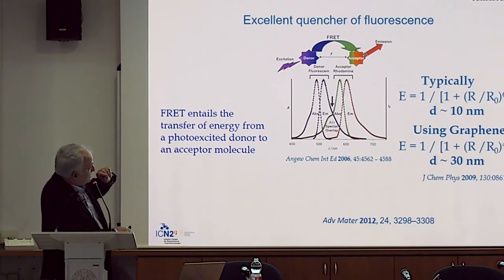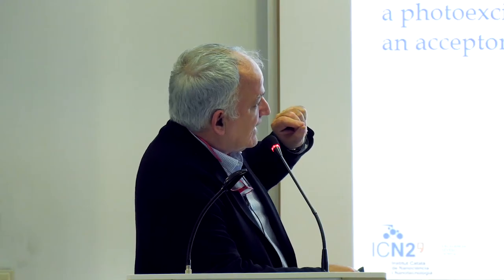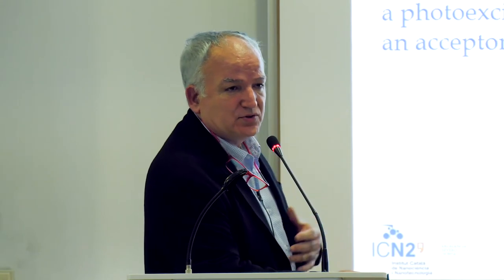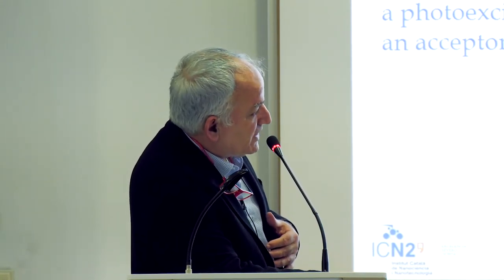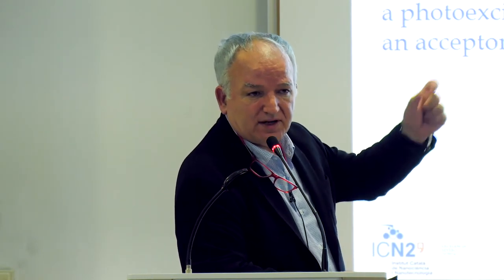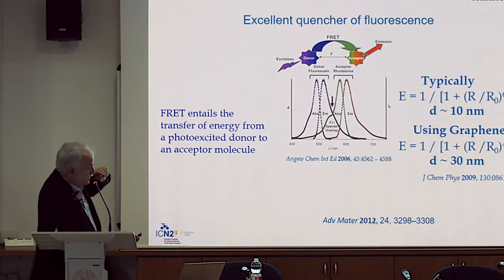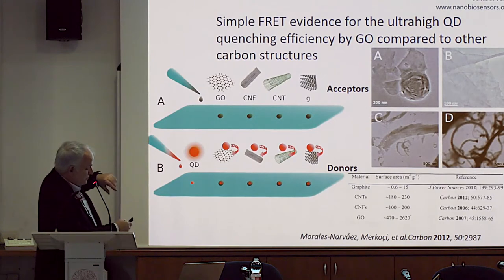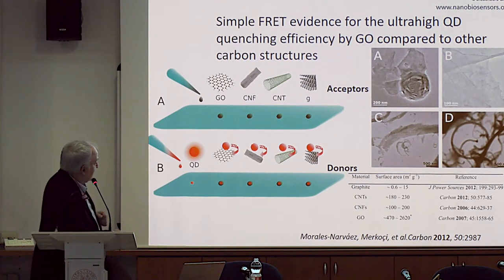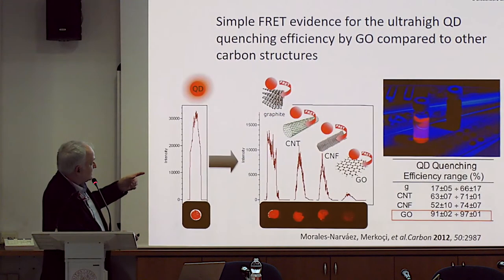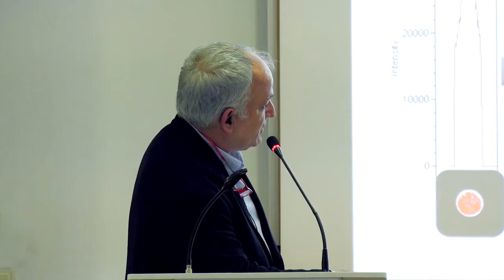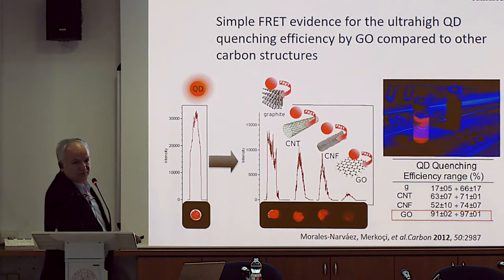Graphene oxide, depending on the distance between the donor and the acceptor, the distance in the case of normal quenchers used in bioanalytical application is around 10 nanometer. In case of graphene oxide, this distance can be even higher, 30 nanometer. And we thought, what can we do with that? And it was really very interesting because we saw that when we use graphene oxide in comparison to other forms of graphite, of carbon, like fibers, nanotubes, and graphite, the quenching, for example, that is induced by graphene oxide toward quantum dots, for example, cadmium selenide, was really very, very efficient. You can see here that we have a total quenching from on to off of quantum dots when you use graphene oxide, almost 90% in comparison to other forms of carbon.